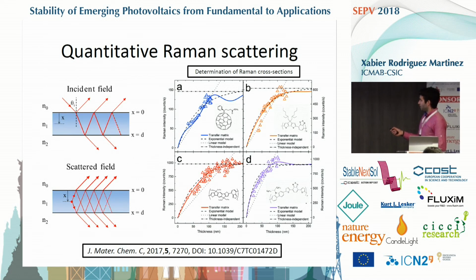The point is that we've been working extensively during the last 2 years in trying to be quantitative with Raman. This means that our initial idea was quantifying the film thickness just by modeling the Raman intensity that we get out of a thin film, and also the volumetric composition in these films, especially trying to apply it to OPV blends. And the result was basically summarized in this paper. I skipped all the equations behind.